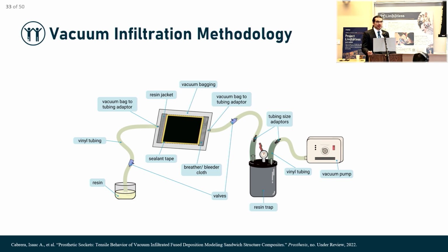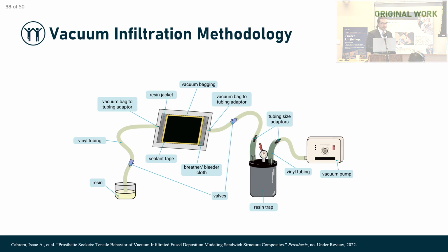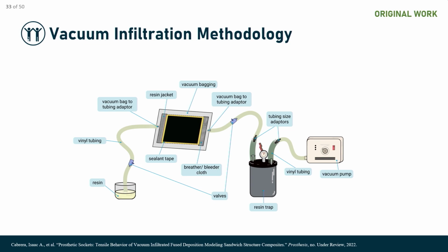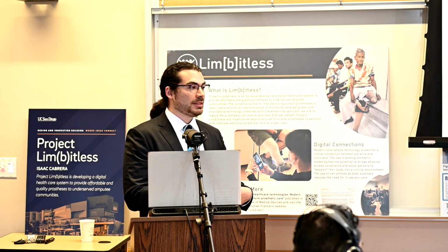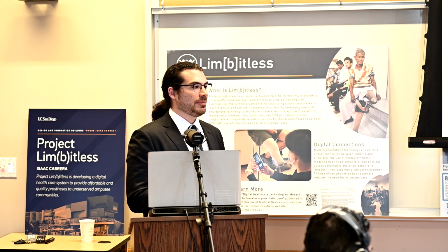Yeah, that is a great question. Essentially, you're limited by the curing time of the polymers that we used. We use two-component resins, where you have a resin and a hardener, and in our case we were looking at which resins were both compliance matching, but really we were looking for the strongest ones we could find. And those particular formulations had really quick setting times.